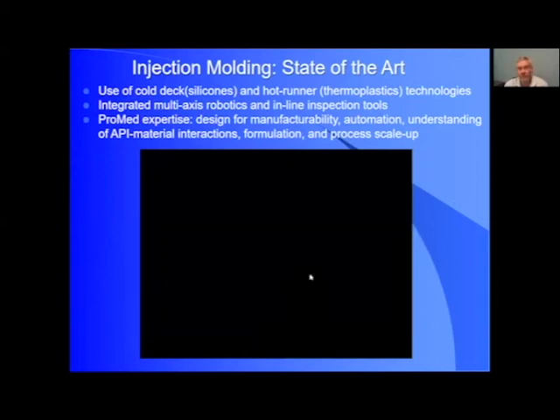So basically, things that you need to do to improve cycle time would be the use of cold decks. Basically, keep the silicone cold right until it hits the hot mold, or hot runners in the case of thermoplastic, right until it hits the cold mold. Using robotics to remove parts and also do inline inspection is within the realm of possibility. And basically, you want to design your complete systems for manufacturability, and in the early stage, understand the polymer API interactions and formulations necessary to have an effective process scale up.